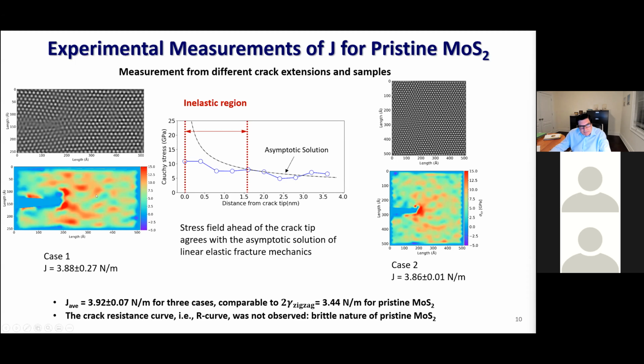So that explains some of these, but you see very nicely stress concentrations at the crack tip, as you expect from asymptotic analysis and finite element analysis. And you can go beyond and say, okay, I use asymptotic analysis, it becomes singular at the tip of the crack, and then the measurement can tell you where the Cauchy stress agrees with the asymptotic analysis and where it diverges, because it is obviously limited by the nonlinear behavior near the crack tip. And the length over which this inelastic region happens, according to these measurements, is on the order of 1.5 angstroms. So the material is quite brittle.